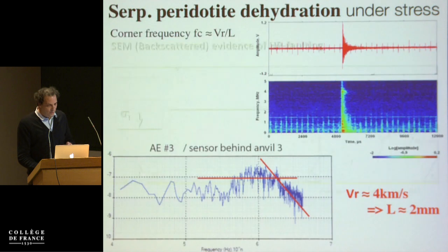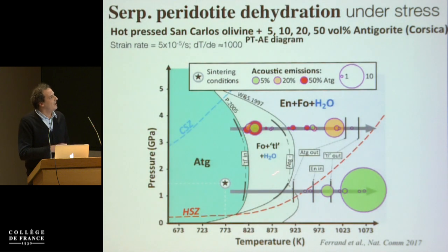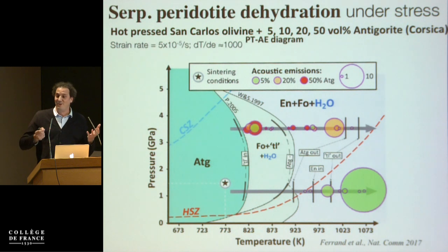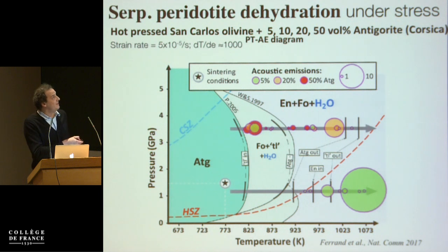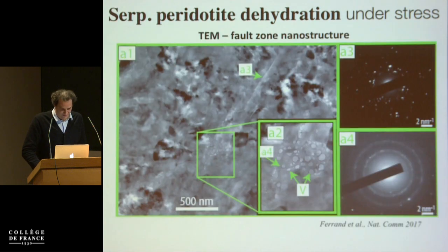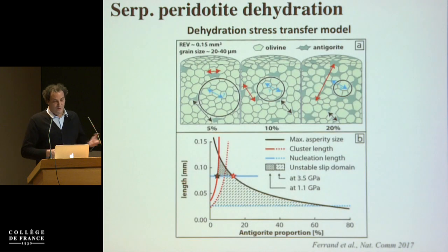However, if you come back to the PT diagram, this is only true where the Clapeyron slope of the reaction is positive. This is not true anymore where the slope is negative. Basically, when the Clapeyron slope of the reaction is negative, you produce water, but you produce more porosity than water. So technically, the pore pressure should drop and not go up. So the fact that we do see earthquakes in this region tells us that the dehydration embrittlement model doesn't seem to work, at least in this condition, because we do.